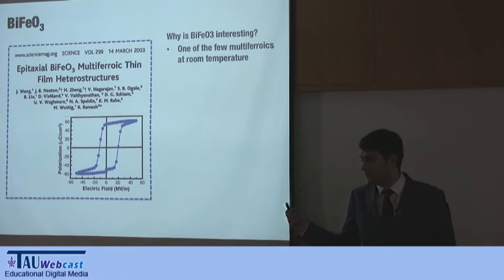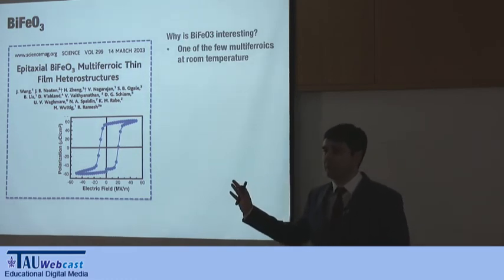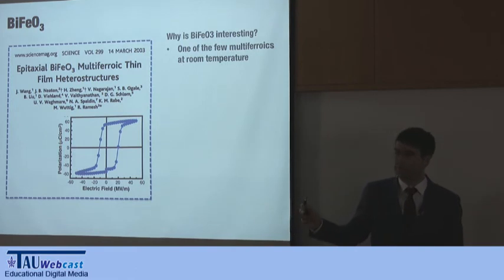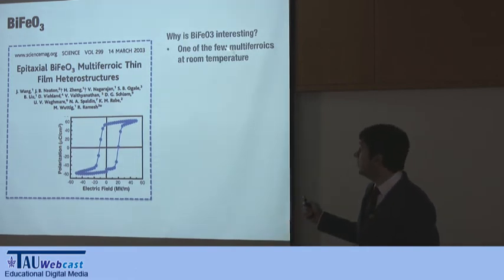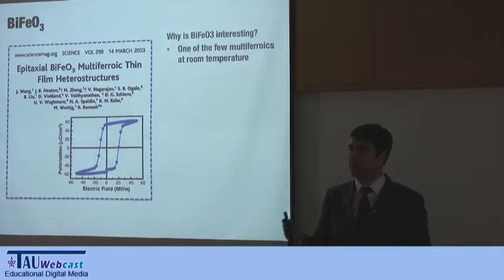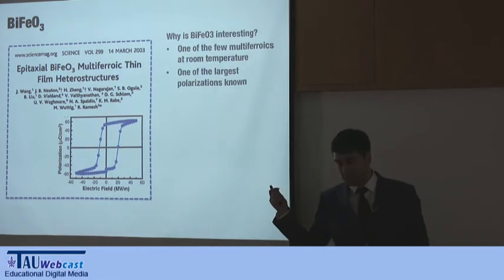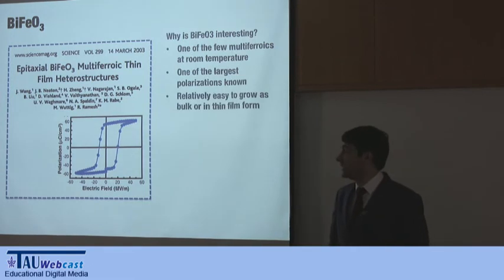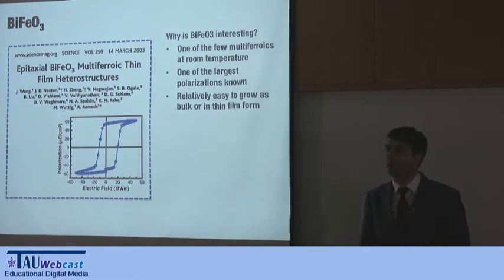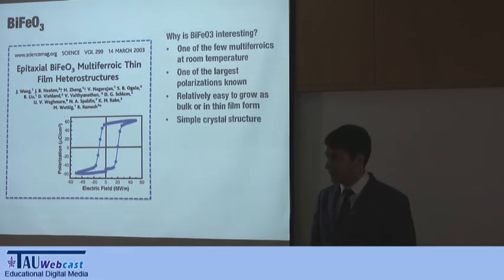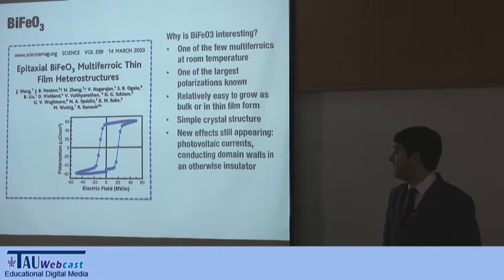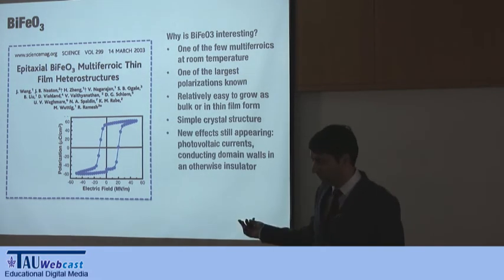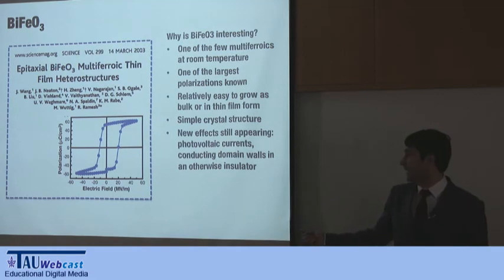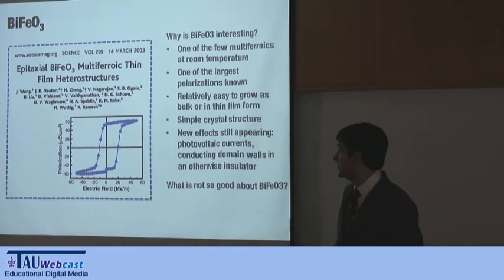So why bismuth ferrite? Half the papers that are about multiferroics are about bismuth ferrite or how to improve on bismuth ferrite, or more than half. Because there are very few multiferroics, and even fewer that are multiferroic at room temperature, which is the temperature you want for your device. As I said, it has one of the largest polarizations known. It's quite easy to grow as a film or as a bulk. It has a very simple structure which helps theoretical studies, and it still shows new effects like very large photovoltaic currents or domain walls that show conductivity.